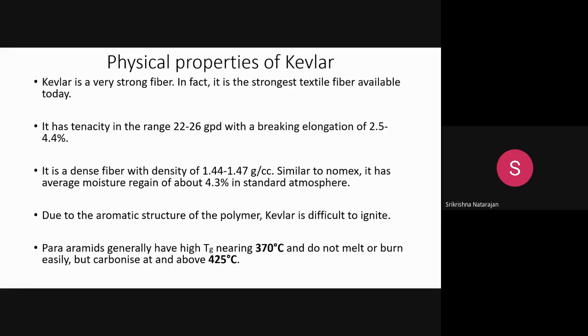So coming down to properties, Kevlar is a very strong fiber. It is the strongest textile fiber available today, and it has a high tenacity, 22 to 26 grams per denier, and breaking elongation of 2.5 to 4%. And it is a dense fiber with a density of around 1.44 to 1.47 grams per cc.